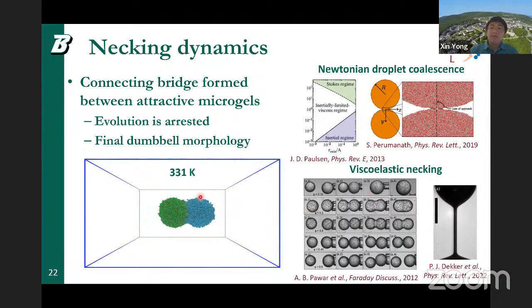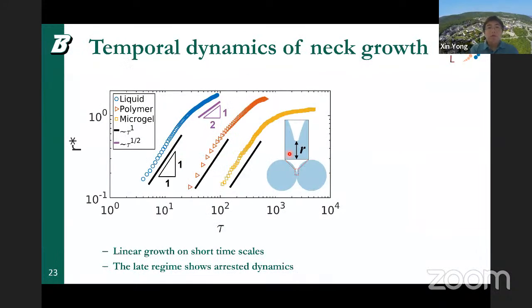So we see that this arrested evolution is very similar to what they see in viscoelastic droplet coalescence. But nobody has ever characterized the detailed dynamics of this neck growth for microgels. So that's what we try to do here using DPD. This is a comparison between three different cases: a pure liquid droplet, a polymer droplet with a short chain polymer, and then a microgel.